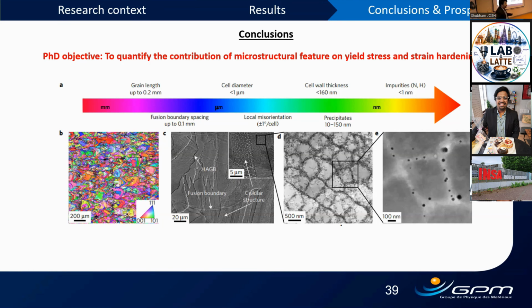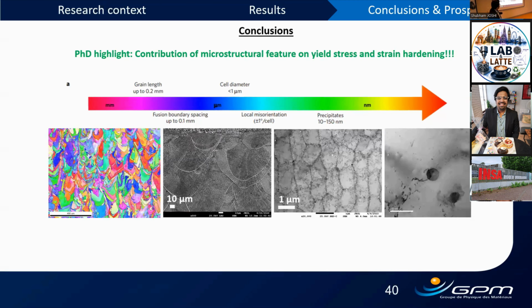So the PhD objective that we set for ourselves, and at least what we are discussing here, is to quantify the contribution of features on yield stress and strain hardening. And in this PhD, we could successfully do a multi-length scale analysis for nickel 20 chromium. And we could also understand that cell diameter less than 1 micron, or these dendritic cellular structures or dendrites, are clearly the most influential parameter to answer both the questions that we asked.